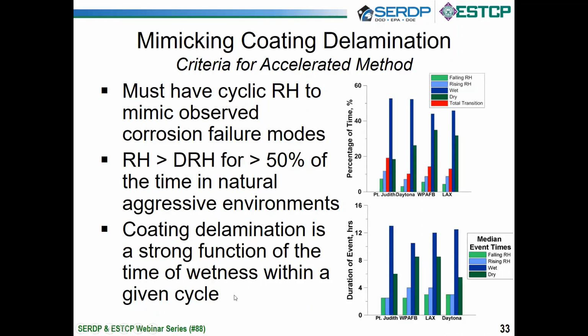In terms of coating delamination, it's a strong function of the time of wetness within a given cycle. So I showed that to you before. Not only did we see the degree of attack change, the amount of corrosion change. I'll show you that a little bit on the next slide. So in this figure here, you can see the total time of wetness in each of these categories. These are during wetting and drying in those intermediate ranges. These red bars here represent the sum of these two. The important thing to note is these are the aggressive environments with their high percentage of time. But again, it's the amount of time in each cycle that's important, right?